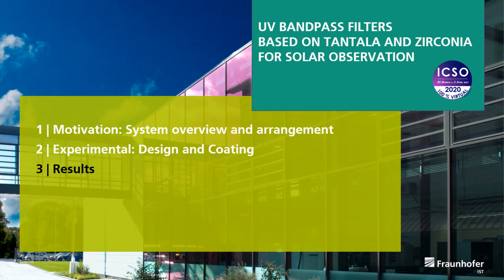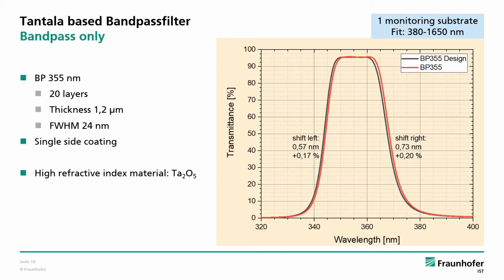Next, I show some results of the filter coatings. We started with a coating of bandpass filters at 399 and 355 nanometers, which could be performed with tantala. First test of a bandpass with 20 layers is shown on the right as red curve compared to the initial design in black. The mismatch from design is only a shift of well below 1 nanometer, but a nice shape.